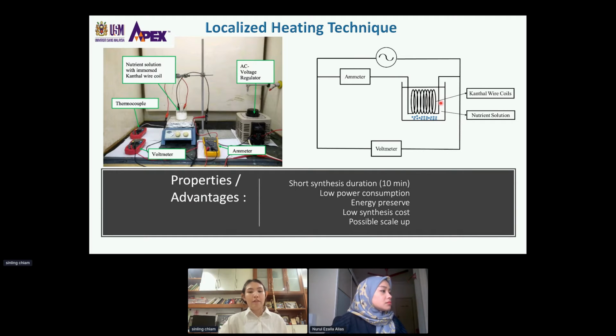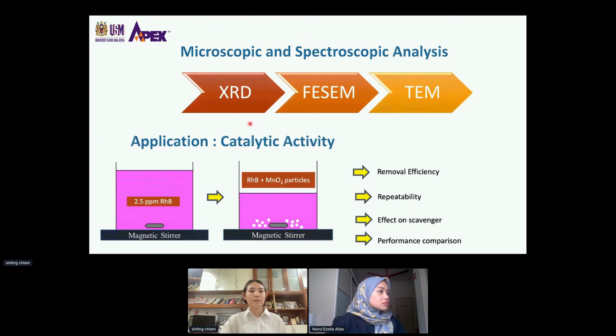Overall, the advantages of this method include short synthesis duration, low power consumption, energy preservation, low synthesis cost, and it is possible to be scaled up. As mentioned, the particles collected after 10 and 15 minutes will be sent for XRD, FESEM, and TEM. Then for application, they will be tested for the degradation of the RhB dye.